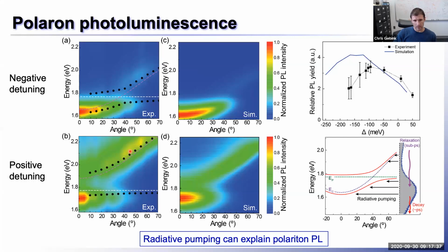And we're able to explain this, at least qualitatively, just with a simple dipole emission transfer matrix calculation. So this is just the usual transfer matrix calculation for dipole emission. And just looking at the distribution of emission, we see qualitative agreement. We also see reasonable qualitative agreement, I would argue, in the relative change in the PL quantum yield between what the transfer matrix model predicts and experiment.